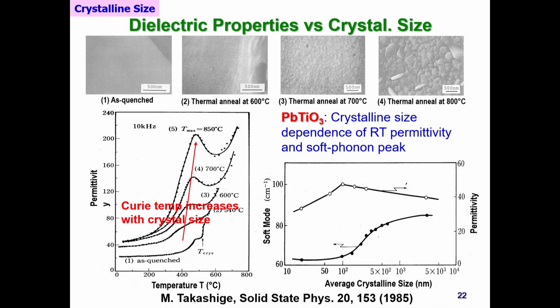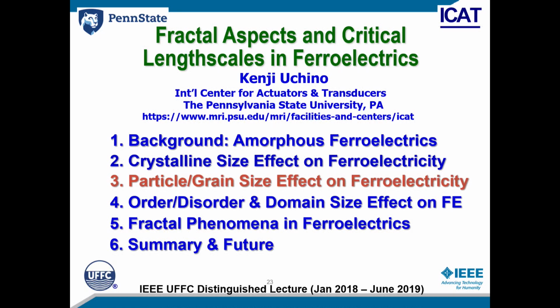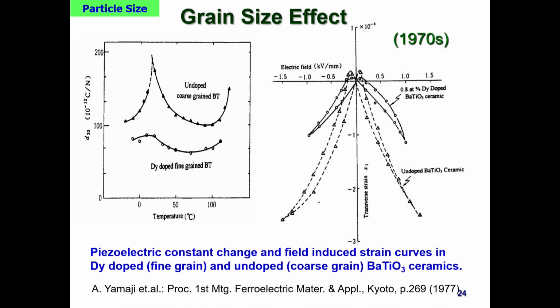Therefore, you can create ferroelectricity inside the already crystalline part. But you know, ferroelectricity needs a minimum of 0.1 micrometer, and this is a 1970s result. So the 0.1 micrometer range is rather critical, okay? And the particle size and grain size effect on ferroelectricity will be thought about. So without making any amorphous phase, we will make small grain size materials.